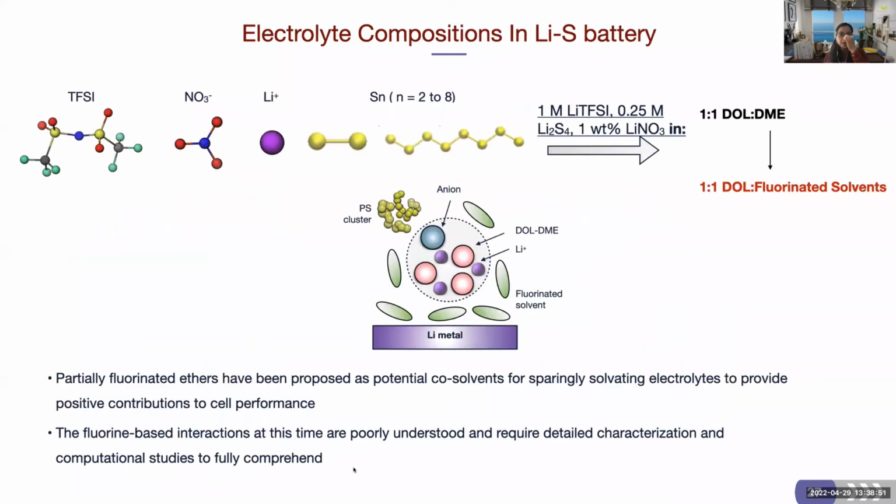So unlike other battery systems, lithium sulfur battery electrolytes are quite complex. The reason being they have a salt, of course, like lithium TFSI. They also often have an additive, which is typically lithium nitrate. And this is dissolved in a binary or sometimes even ternary solvent mixture. The state-of-the-art system is the DOL-DME mixture.